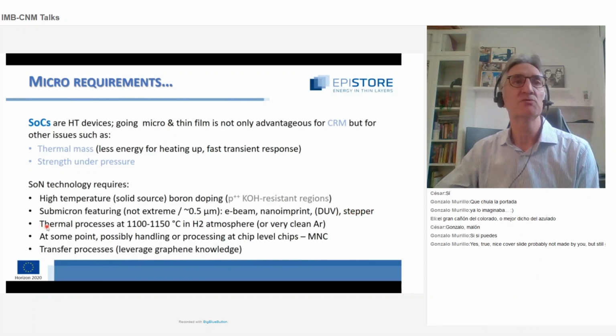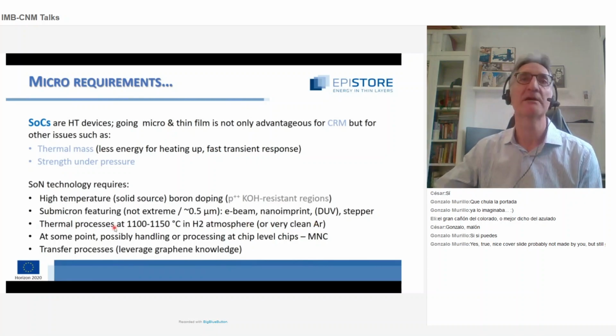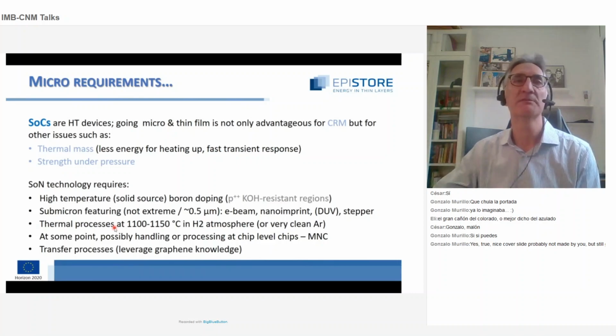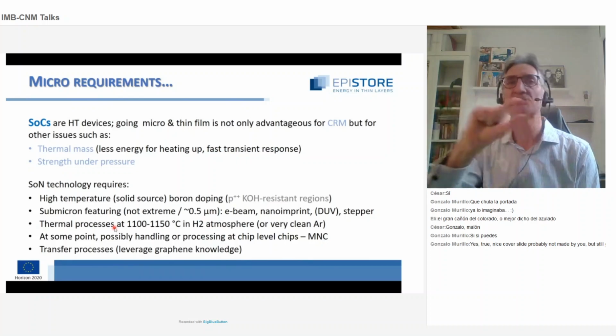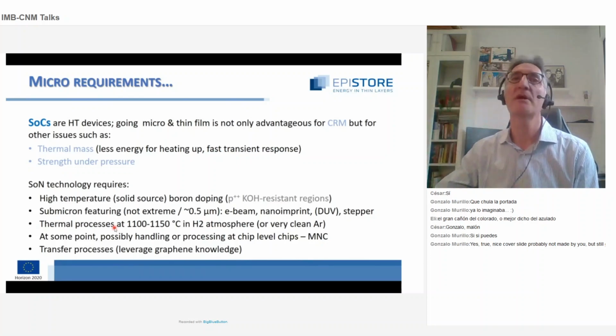And also, we need to be able to perform thermal processes at high temperature, and this is important, in hydrogen atmospheres or very, very clean argon. Okay, if not, you cannot get those pillars becoming spheres and then becoming a surface silicon skin. By the way, this silicon skin will be 1 micron thick, and the air gap will also be 1 micron thick.